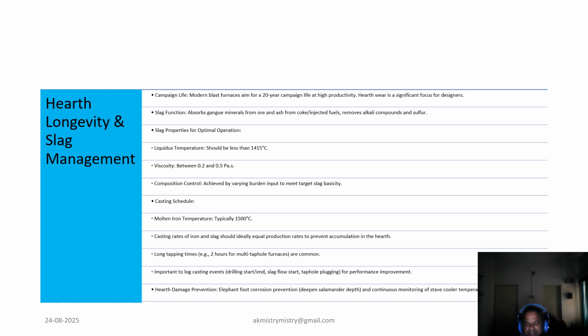Slag composition is critical, especially quaternary basicity, which has a great influence on slag viscosity, with a sharp increase when R4 exceeds 1.1. The hot face structure is meticulously designed and monitored for heat transmission. Creep deformation of a copper stave, particularly when cycling between high and low heat loads like 1050 kilowatts per square meter, is a critical factor influencing deformation. This creep combined with thermal cycling is a suspected cause of cracking in stave hot faces.